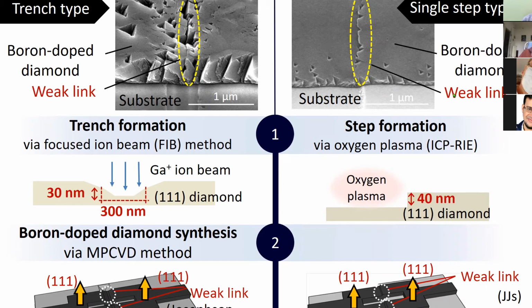The substrate is also diamond, but these heavily doped regions appear a little dark in the image. This is the SEM image, so I don't know why it's gone dark, but anyway, here in a bit, this is not the surface but regions a little near the interface, where weak links take place, and then the Josephson junction would be made.